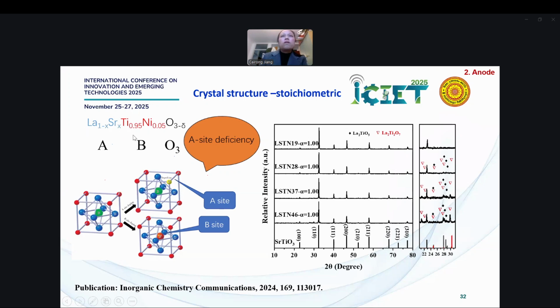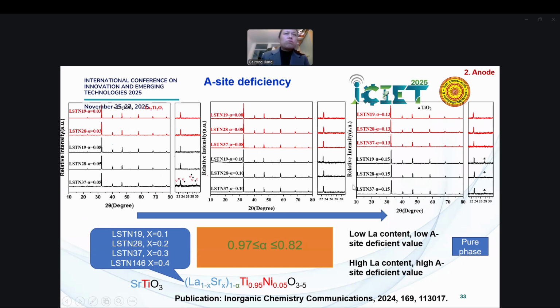We just made a stoichiometric material, and alpha here, alpha means 1, means it is stoichiometric. There's no change on this value. I kept it at 1, but it's difficult to get a pure phase. We tried different compositions with different lanthanum content, like I've shown here. It's all impurities, so it's not good to be used. So we think maybe there's a way. We try to use A-site deficiency.